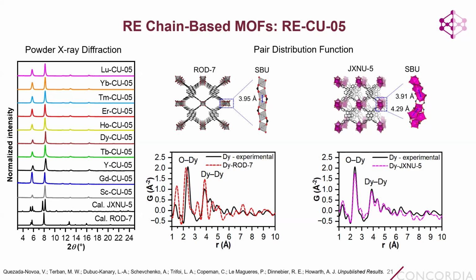So from there, we turn to this total scattering data and specifically to the pair distribution function analysis. And so, as I mentioned, Victor collected this data at the ESRF. And so we compared the pair distribution function, specifically from 1 to 10 angstroms, for the experimental data for this MOF that we were calling Dy-CU-05 to models that Victor made, taking the JXNU5 MOF that had been previously reported and just inserting dysprosium into the material, and taking this ROD7 MOF, which had been previously reported, but switching the metal for dysprosium.